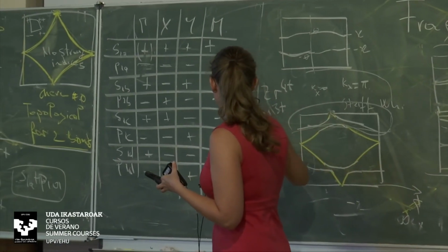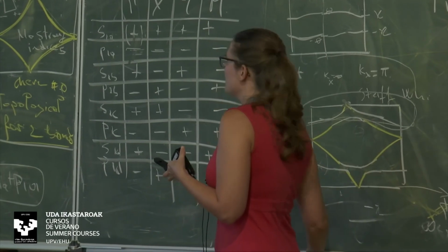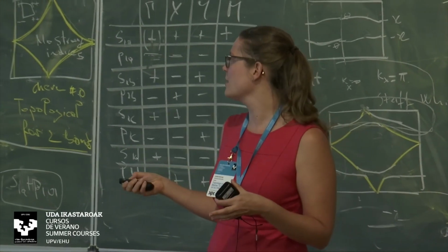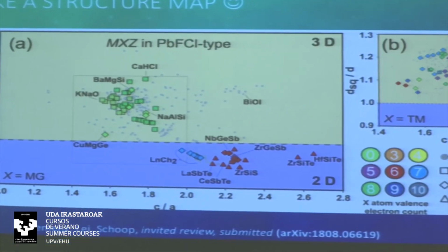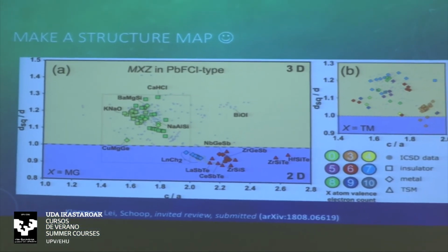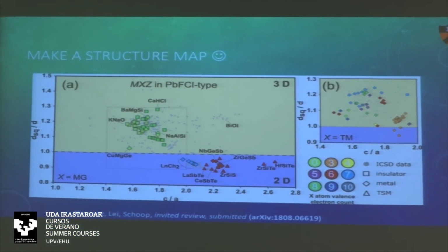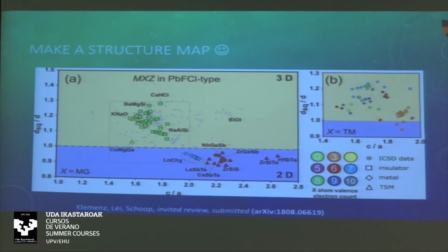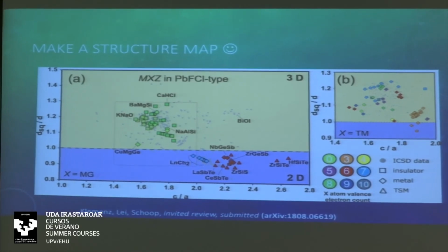But if we have 5+, like in these niobium compounds here, so these metallic ones, or dirty ones, they would have a 5+ oxidation state. So there is like too much of the good. There's too many. So if 4+ is already only a formality of an oxidation state and not fully there, 5+ is even worse. This niobium will never be 5+, so it has a lot of d electrons still floating around, and they mess up your band structure.